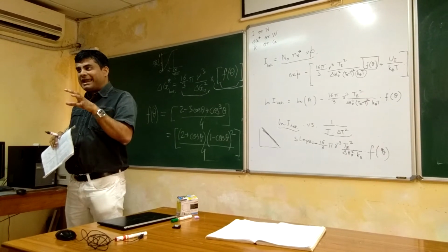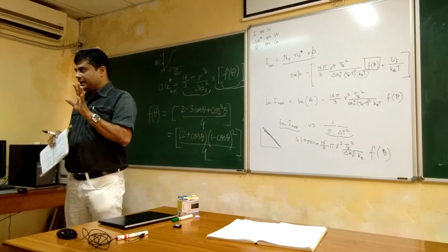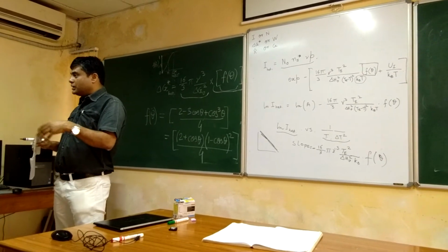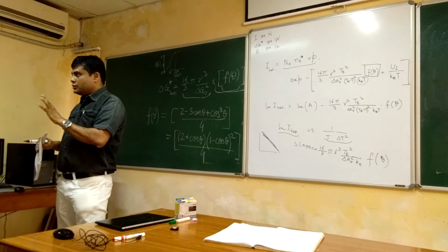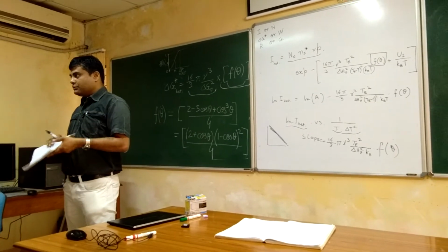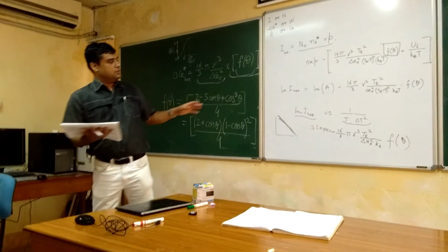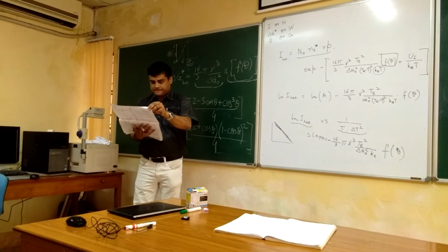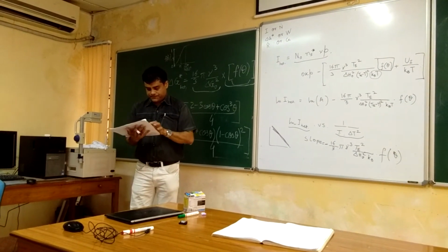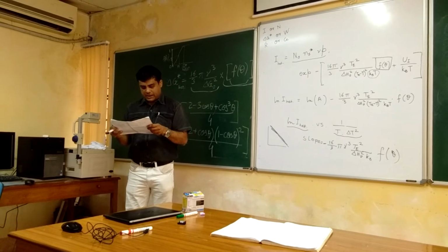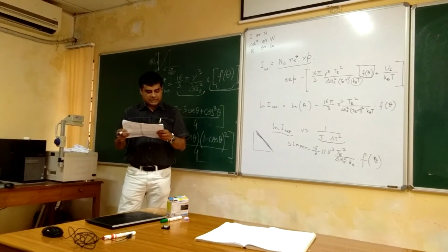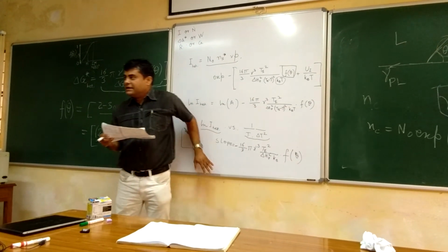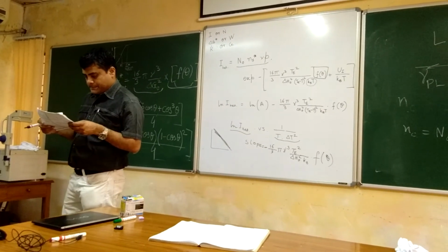So nucleation rate is mainly dominating; that is the slowest step. Overall solidification rate you can measure, so he equated it with nucleation rate. That's how all this analysis was done. And you can find out theta from the slope if you know the gamma value.